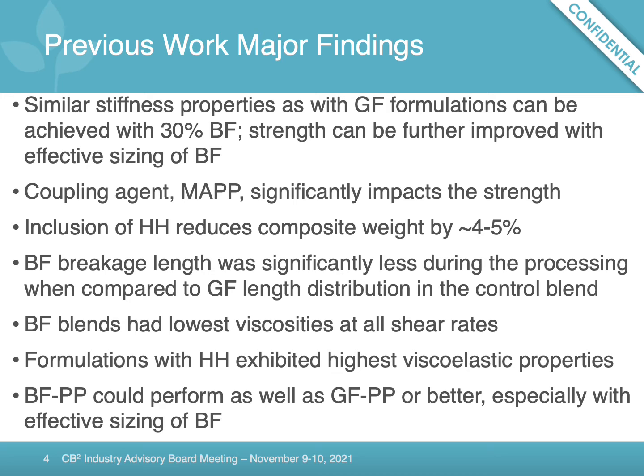We found that with 30% basalt fiber in the formulation, it can yield composite material that has similar stiffness to glass fiber formulations. And with inclusion of sized basalt fiber and coupling agent, we can also achieve strength properties similar to glass fiber. And inclusion of hemp-hurd reduced the weight of the composite material on average by 4 to 5%.